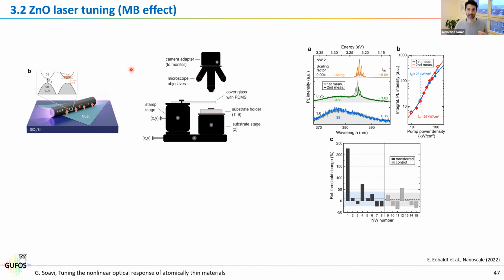But the reason that triggered our research in this field was the finding that by basically using the same microscope that we use for the mechanical and deterministic transfer of 2D materials, so this is the commercial microscope from HQ Graphene, we can use the same method and the same PDMS stamp also to transfer the nanowire. So typically when you want to combine nanowires with 2D materials, people have done it with stochastic methods. So you have your nanowires, you use, let's say, a drop casting method, and somewhere on your device you will have nanowires sitting on the TMD.